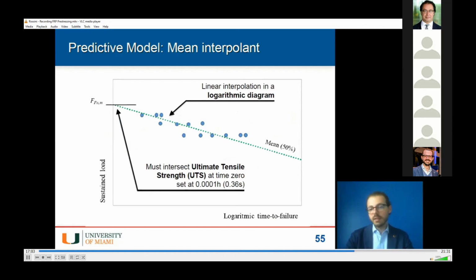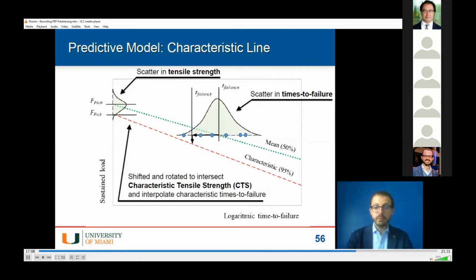Interpolating lines, interpolating points is not enough to predict the design value. We need to account for variability in our numbers, and we have scatter both along the time axis in our times to failure and along the strength axis in the strength of our material. Accounting for that through statistical modeling, we can shift and rotate our main interpolation line and define a characteristic interpolant that takes care of 95% of our failure points.